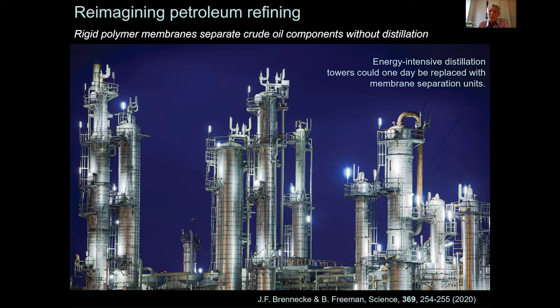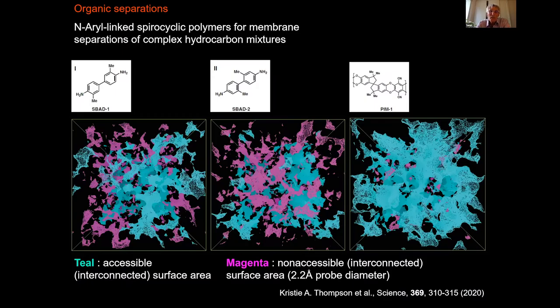What people in this paper succeeded to do is to make a membrane with pores of a narrow size distribution around a few angstrom in a polymer which was rigid enough to not swell and not dissolve in the presence of the molecules of crude oils. And they were able to do the equivalent of distillation, of course, by applying quite a lot of pressure to the device. And of course, they didn't look at the mechanics of the thing, but this is probably a very interesting paramechanics problem with a multiplicity of fluids going in parallel into different populations of pore sizes.